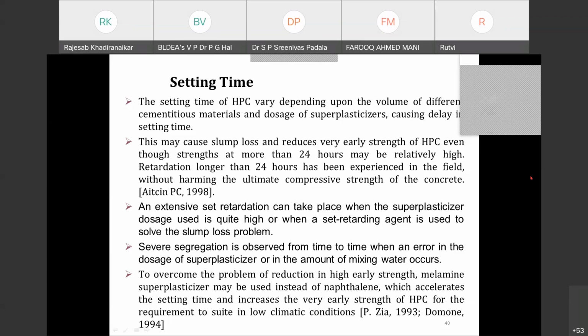Of course, for the initial setting, if you go for a higher percentage, particularly more than 2%, then 2%, 3%, 4% like that, in some cases there will be retardation, which means the setting is delayed. Even after 24 hours it will not set; sometimes 48 hours, 50 hours, 60 hours. In some cases in our own laboratory, with one particular brand of superplasticizer, we were not able to get the setting even after 72 hours. So all these things must be observed.